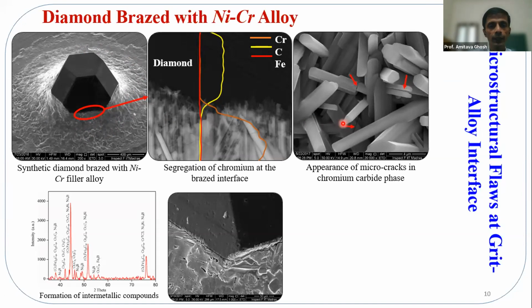Now, when we cool the entire system from the high temperature, this nickel chromium alloy I'm talking about has a liquidus temperature, so I need to set the brazing temperature very close to 1000 degrees centigrade to realize the brazing. So from 1000 degrees centigrade, we allow it to cool. That induces stress because the diamond contracts at a different rate, the substrate contracts at a different rate, and in between this alloy has to absorb that stress. The alloy is nickel based, so it should be supportive enough, but you have chromium carbide at the interface. This chromium is the active element in this alloy matrix.